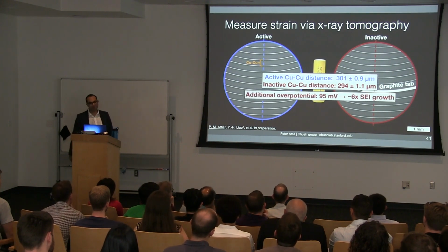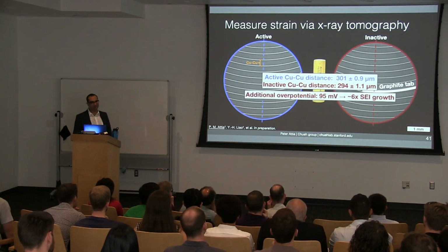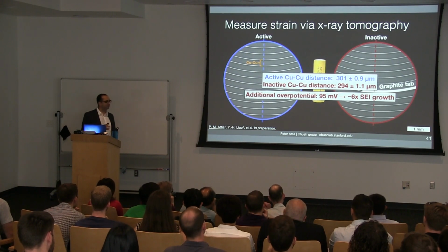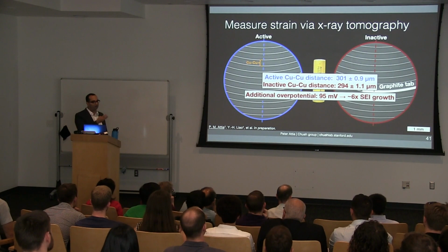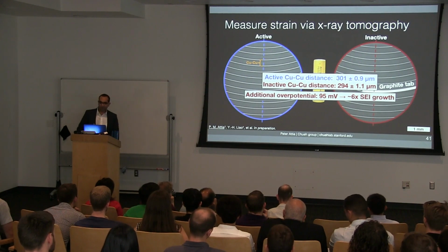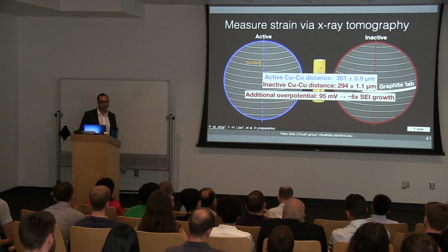Now, I don't have time to go through all the math here, but we estimate that the 7 micron difference in thickness leads to an additional 95 millivolts of potential. And based on our measurements of SEI voltage dependence from part 1, this corresponds to a 6-fold difference in SEI growth between the active and inactive regions. So it's reasonable here to see how small differences on the cell level can lead to large differences on the nanometer level.